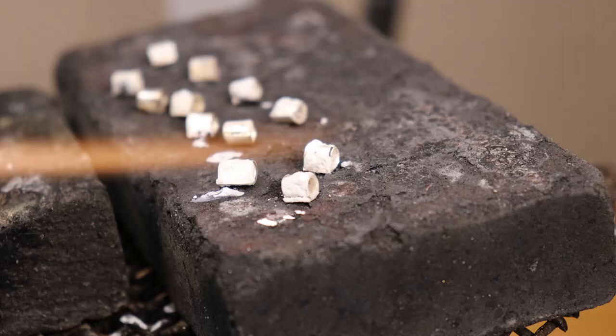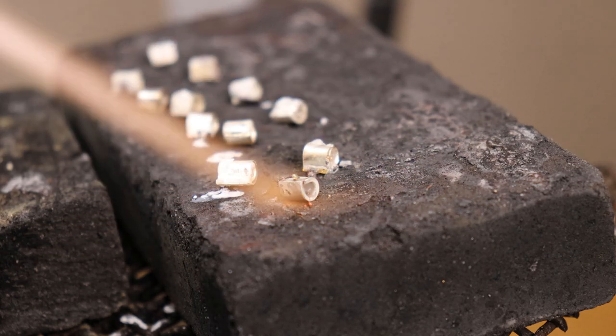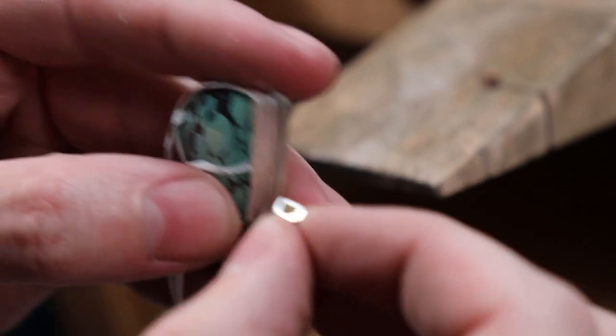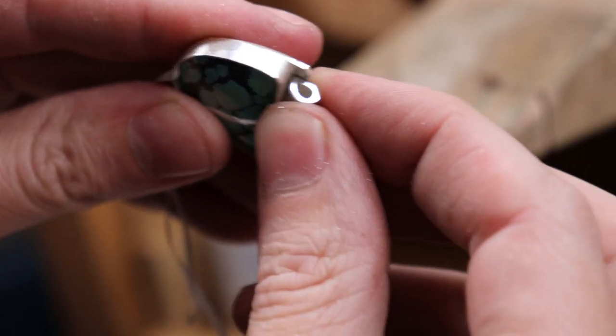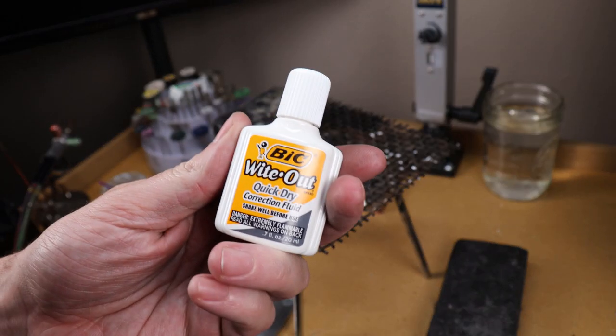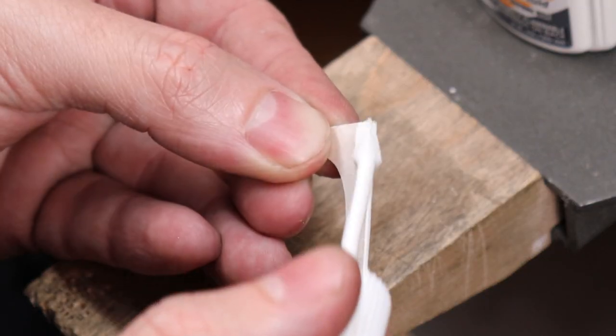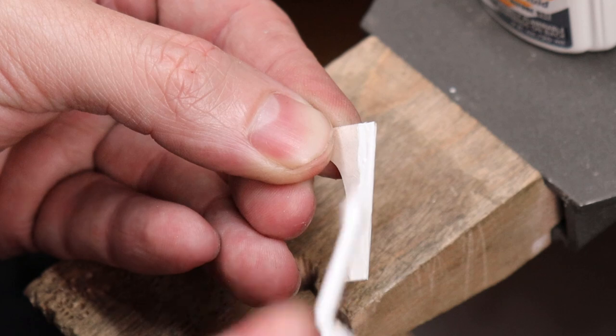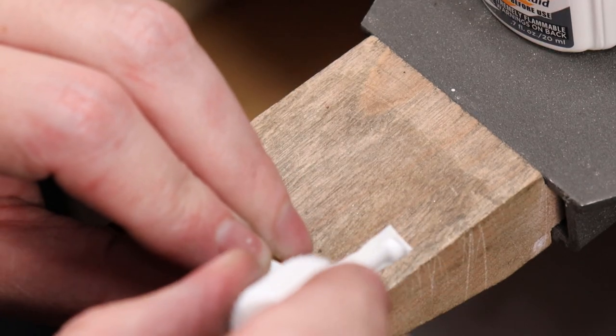When it comes to soldering them, I'm just going to flux the bottom of them and then pick solder every single one of them with medium solder. So to solder these in the place where I need them, they need supports because they'll just fall off otherwise. And I don't want them to get stuck to the support material. So you can use whiteout, and it'll make it so nothing will stick to whatever has the whiteout on it. As for the support piece, I'm actually going to be using one of the cutoff pieces from the backplate, so it's exactly the same size and everything lines up.